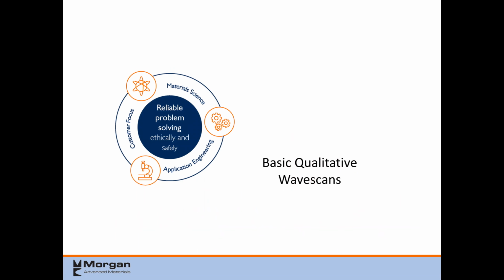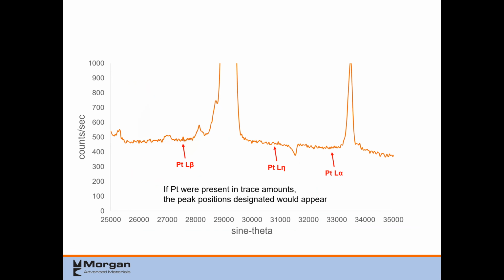So let's talk about some qualitative wave scans and uses for those. So this was a project where they knew there was a contaminant in their material, and they guessed that it was a platinum contaminant. So they wanted to know how much platinum was there that was causing a problem. But when I looked for platinum, I actually didn't find any. So I told them it doesn't have platinum. That's not your contaminant, because there's no peaks where the platinum lines would be.